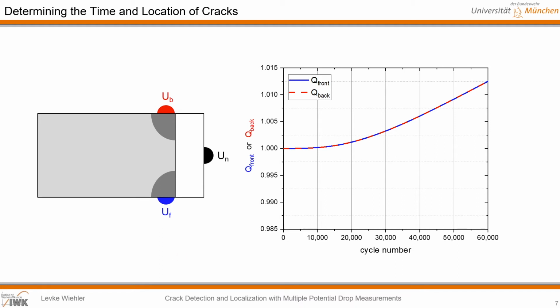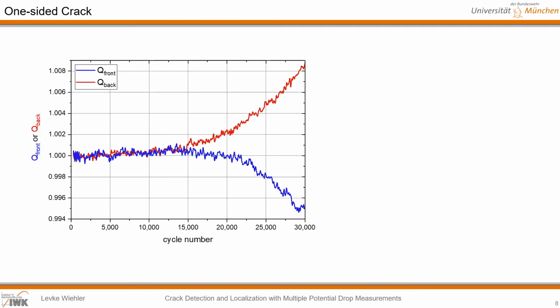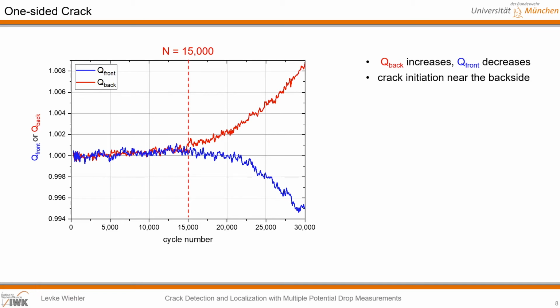These criteria can be used to describe the first crack as well as subsequent cracks. In the following, I will present to you those cases on different samples. In sample 1, both quotients initially remain constant until the first overload after 15,000 cycles. At that point, the quotient Q back increases while the quotient Q front decreases. According to the categorization, the first crack is expected near the back of the specimen.